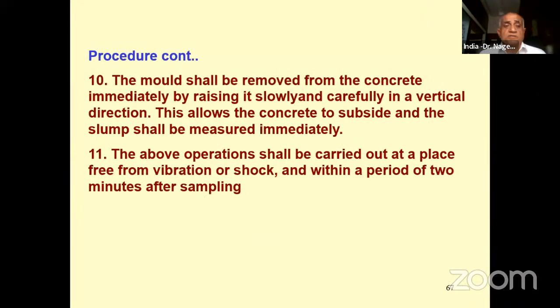So here comes the usage. Then the mold shall be removed from the concrete immediately by raising it slowly and carefully in a vertical direction. This allows the concrete to subside, and the slump value shall be measured immediately. So the height of the concrete gets reduced. It can get reduced by only 20 mm, 40 mm, 60 mm, 80 mm or 100 mm. In case of highly flowing concrete, instead of vertical slump, it becomes a horizontal flow, in highly workable concrete mixes.